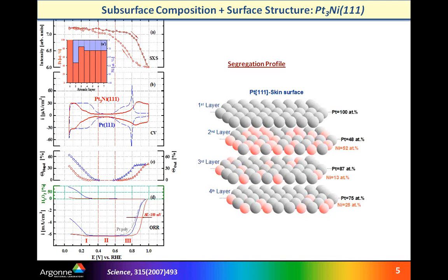First of all, there is this unique oscillatory concentration profile, which we are calling the nanosegregated profile. There are also unique electronic properties of the platinum surface atoms. This is the d-band center position, which is controlling adsorption and catalytic processes. The key, at least with voltammetry, which is in the middle, is that due to the lowering of the d-band center, adsorption of hydrogen and OH species is significantly reduced.